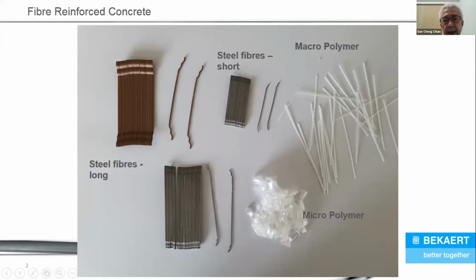Back in the first KV MRT Line 1 project, at the very beginning, they were testing fibers with a tensile strength of 1,200 megapascal. And with that, it was impossible to achieve the high FRC requirements because the fiber keep on breaking at the end. So later, what we did was we introduced a fiber with a tensile strength of 1,550. And with that, we could solve the fiber breaking problem.